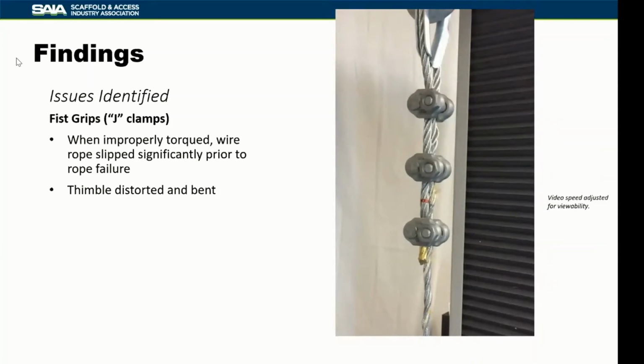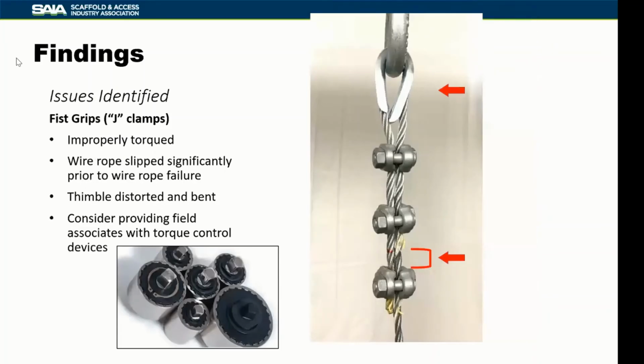Okay, and after this particular test was conducted, you can see how much deformation we got in the thimble. And you can see from where that red mark was placed on the wire rope at the lower fist grip, how much that moved throughout the course of the test. So even though we do get failure in the wire rope, you can see that you are definitely moving the wire rope through those fist grips.